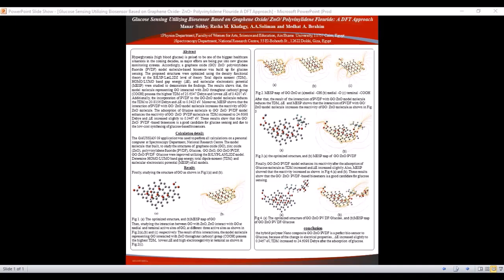The proposed structures were optimized using the density functional theory at B3LYP and LANL2DZ level of theory. Total dipole moment, HOMO-LUMO band gap energy, and molecular electrostatic potential were studied to demonstrate the findings. Firstly, building the model molecule of graphene oxide. After that, finding the total dipole moment and HOMO-LUMO band gap energy with molecular electrostatic potential of graphene oxide.